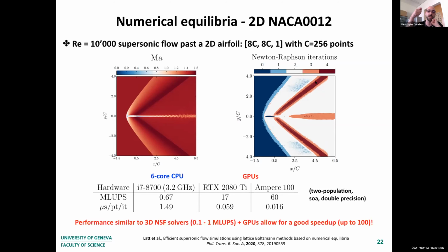And this can be explained here by the fact that even though we rely on an iterative manner to compute the equilibrium, the number of iterations of the root finding solver is approximately 2 on average, which is rather small, and it can go up to 4 iterations when we get closer and closer to the stability limit of the model, which is here a Mach number of 2.